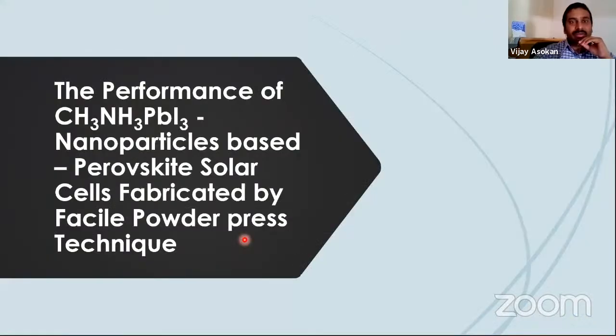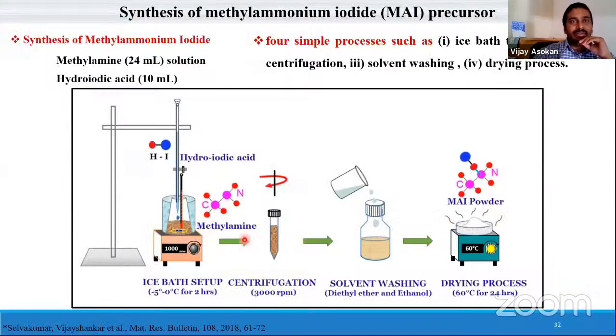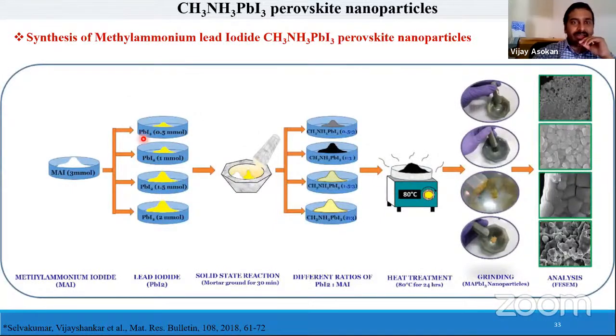So first we consider the performance of perovskite and nanoparticles based solar cell devices. We synthesized methyl ammonium iodide by such reactions. Even we published it in Material Research Bulletin in 2018. We have made a 4 simple process like ice bath treatment, centrifugation, solvent washing, and dry processes, and make first methyl ammonium iodide powder. Then we use such things with lead iodide with different molar combinations by using a solid state reactions with different ratios, then heat treatment, grinding, which makes different structural synthesis of different perovskite nanoparticles synthesized with